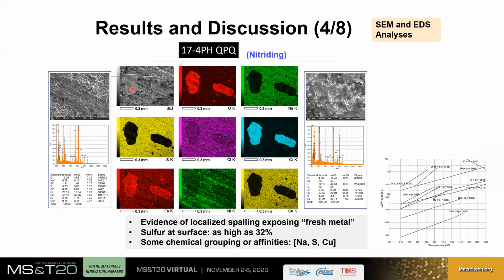So why is it missing? Well, if we look at the chemical compositions here and there, what we see is that the coating has actually reacted tremendously with the H2S. In fact, the top layer here is comprised of approximately 32% of sulfur, while what you see underneath essentially is closer to being the bare metal. Okay, so what we're seeing is quite a bit of sulfur,